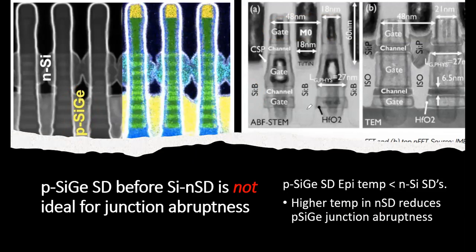And that high temperature, the thermal budget, the thermal history, will diffuse the boron inside the silicon germanium. The boron's diffusivity is higher because of germanium, right? And then that will change your junction properties. So that's one of the problems I see here. It's not an easy thing to do.